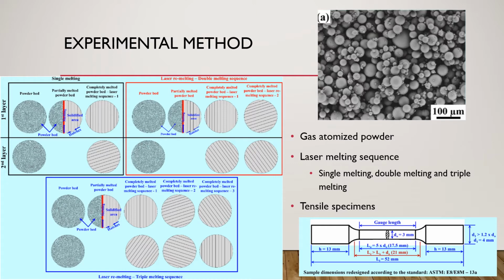Double melting is when the laser scans the powder very selectively to melt the powder, and after it solidifies, the surface is scanned again by the laser with the same process parameters, but this time its hatch style is rotated to remelt the solidified part. So once it is solidified, the second layer of powder is deposited and the process iterates until done.